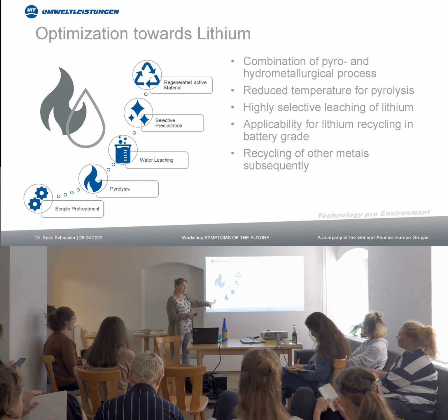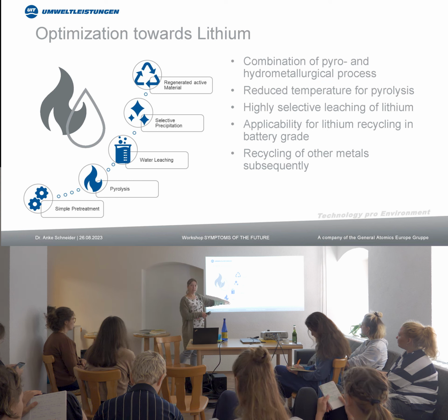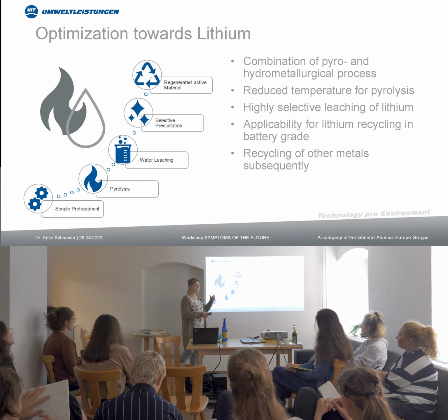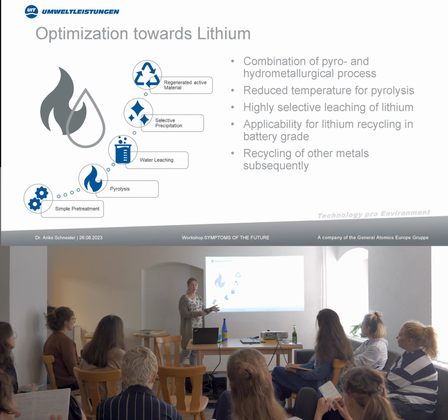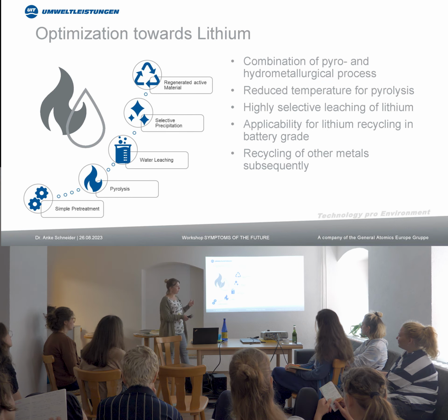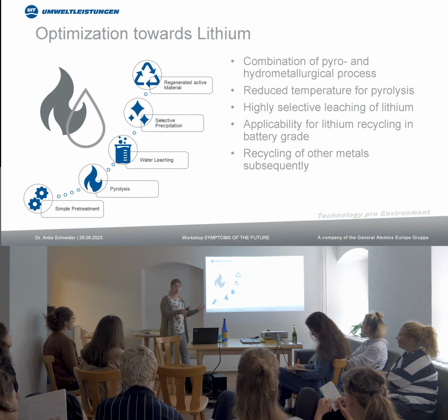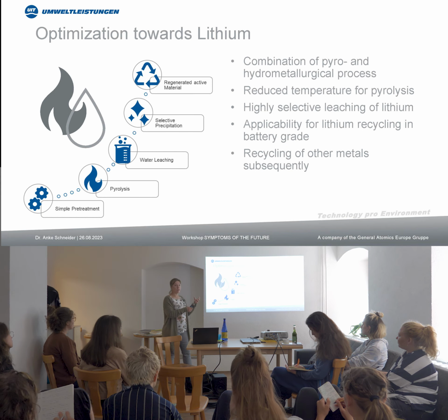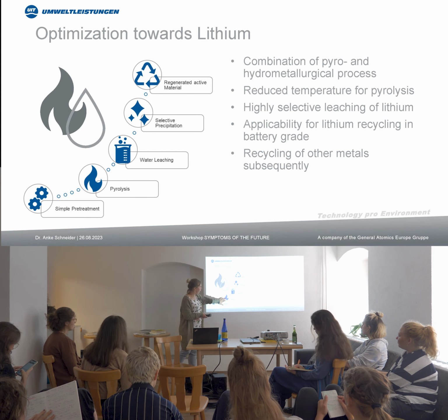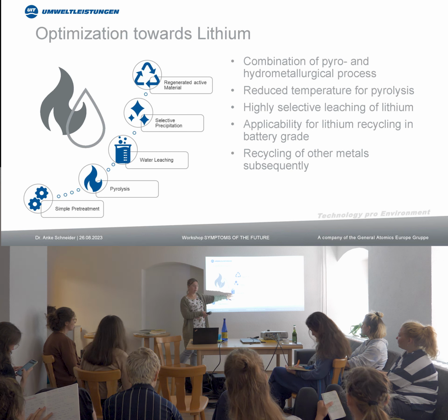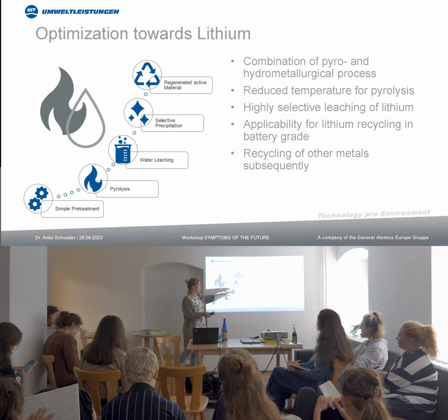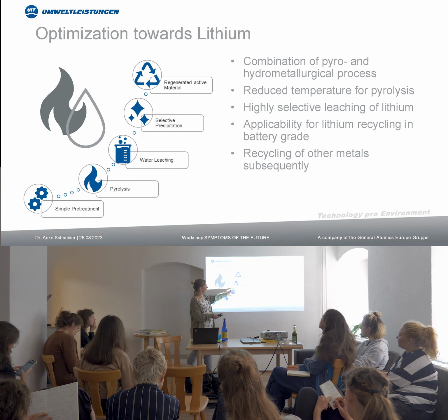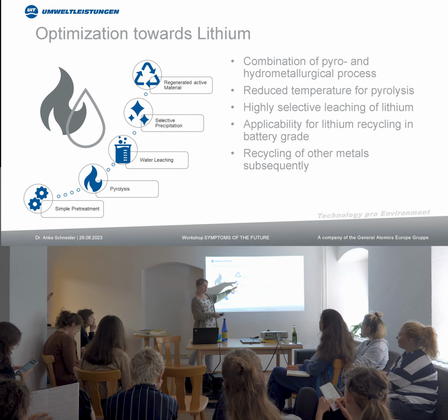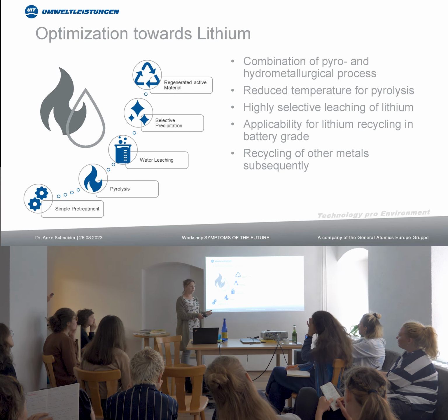So you have an easy preparation because at the first end you have a pyro process. However, this pyro process is called pyrolysis. It's not at as high temperatures as in the other process. So you're around 500 to 600 degrees Celsius, and under vacuum, so you don't have an off-gas. So you can specifically treat your off-gas. Of course, you're producing gases. Then you don't have an acid leach, but a water leach, because during this pyrolysis, you convert the lithium into a salt, which is easily water leachable. And because you have a very selective leaching, you have a very selective precipitation and a high-quality lithium you can achieve with this process.